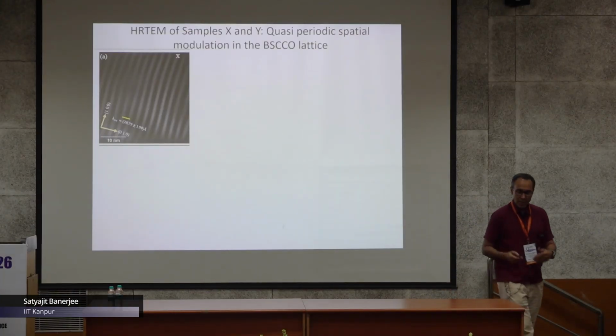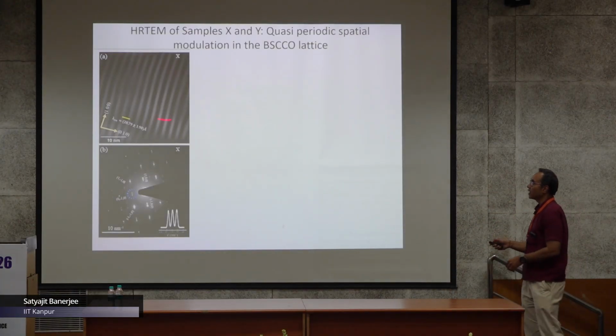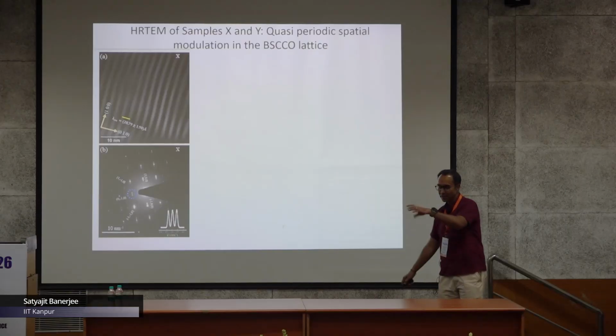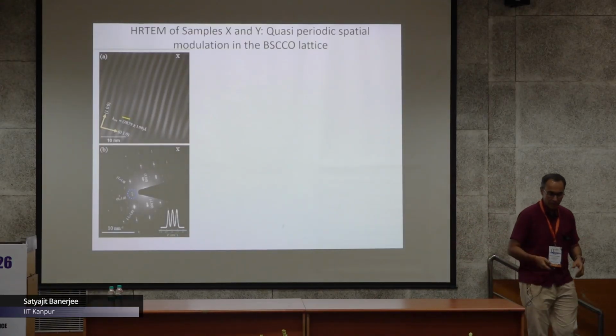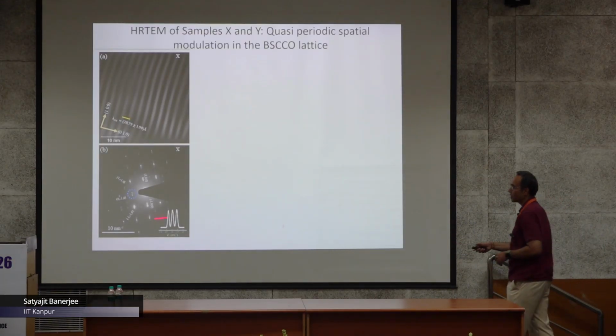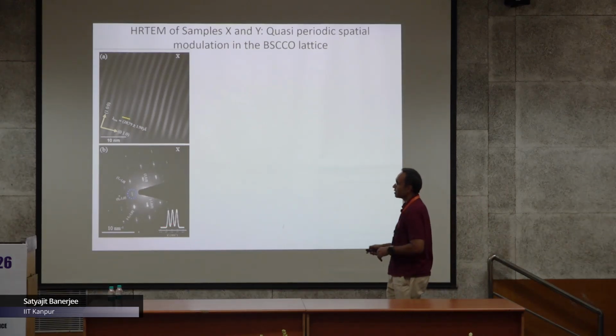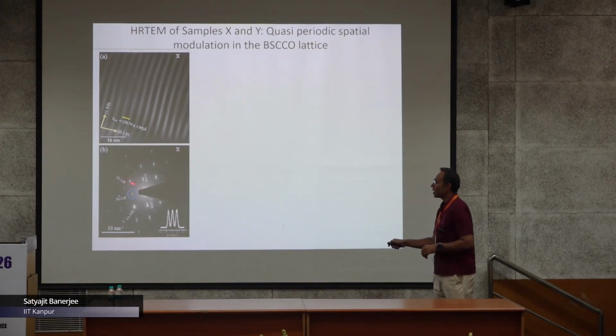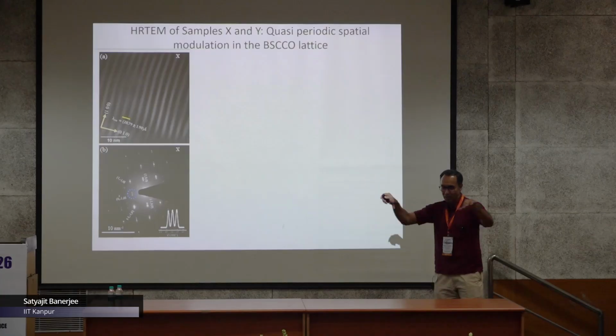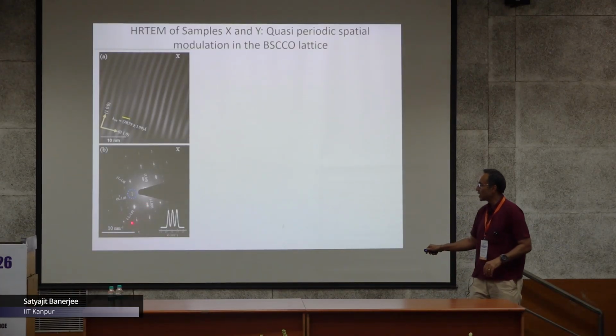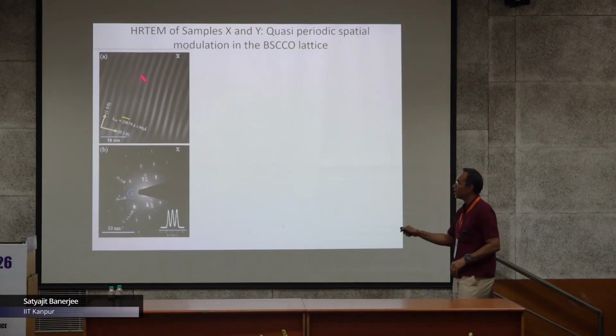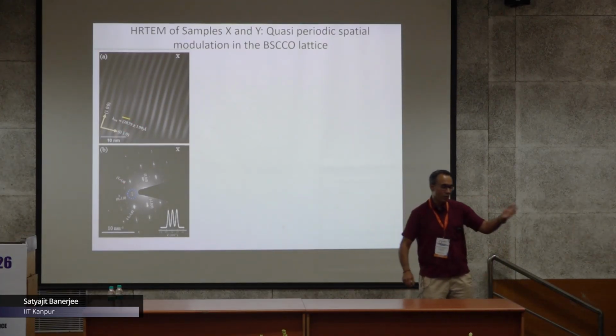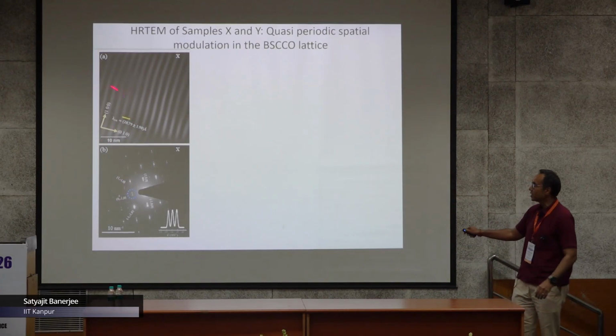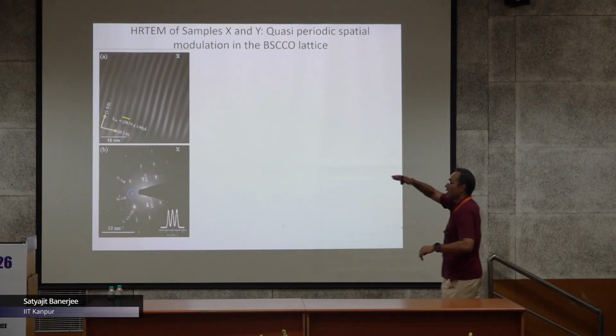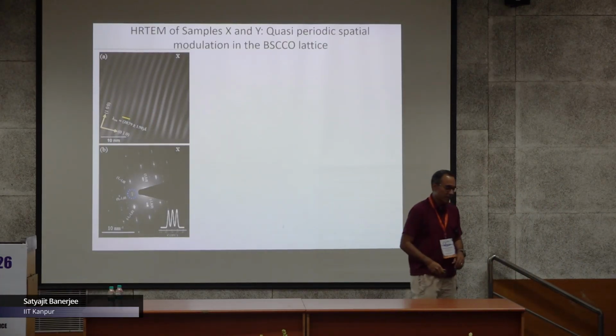This is further confirmed if you take a selected area diffraction pattern—basically you look at the Fourier transform by shining electrons on the system, and then look at the SADP. Apart from the actual Bragg spots which come from the crystalline structure, you will see satellite peaks. Each spot is surrounded by 3 other spots, which comes because of the different Q associated with the second periodicity, this modulation present inside the crystal.